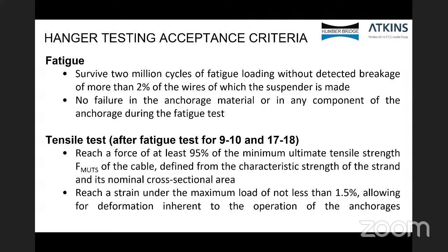So the hanger testing acceptance criteria for the fatigue: if the hangers were able to survive 2 million cycles without detected breakage of more than 2% of the wires, then it was deemed successful. As long as there was no failure in the anchorage material or any components of the anchorage during the fatigue test, I would consider the fatigue test to be passed.